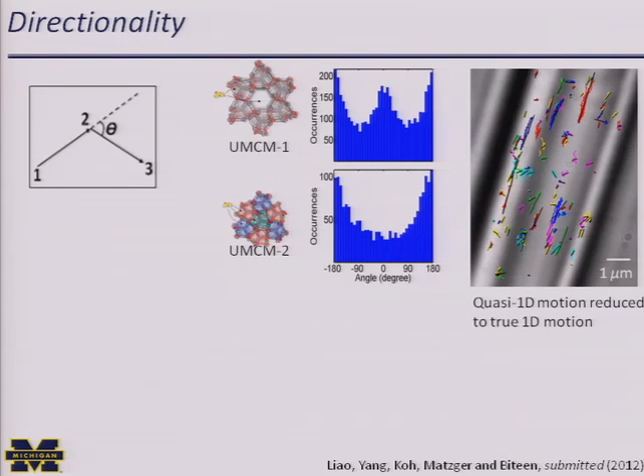For UMCM2, which mostly had confined motion, we actually see a distribution of angles, but this is the distribution that's characteristic of a Gaussian error in localization. Because if a molecule is right here, it could be localized there, there, there, there. As we move further from the center, there's more chance that the next step will be closer to the center. So these are very small steps, but they end up giving rise to this distribution. So we're not going to think about UMCM2 anymore in this motion analysis.